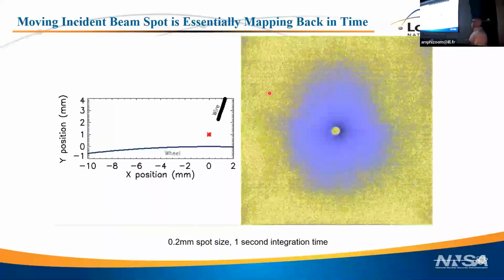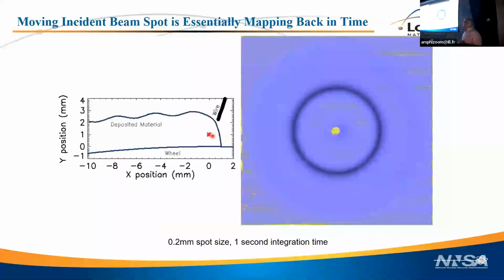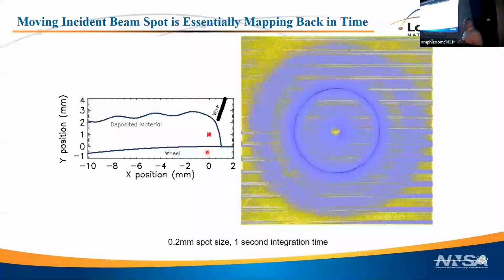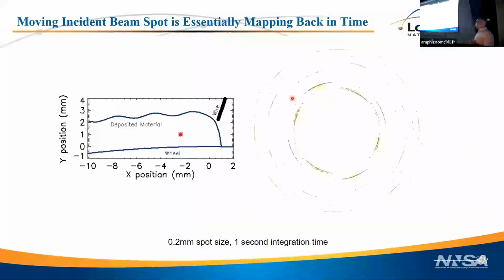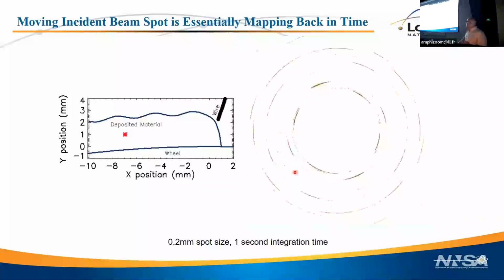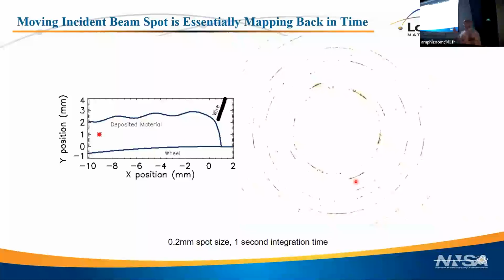So this is a movie of what some of that data looks like, and here's a schematic. This is where the beam is for each of these images. So you can see there's the nice rings that come with diffraction. We actually move forward, and then we go through, there's the liquid. So now, because we're doing it much slower, we go through the liquid, and then it solidifies. You can see the crystallographic texture. You see the fourfold symmetry in this peak intensity. As you go around, that is the FCC 200 peak. So you see the texture is not actually symmetric. It's tilted towards the cold side of the deposit, which isn't too surprising, although we didn't expect it. That's what the raw data looks like.